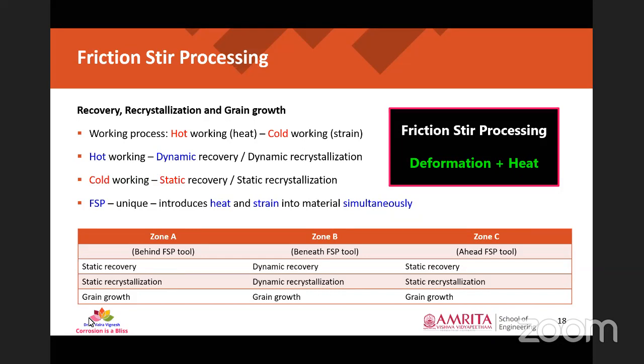Okay, so generally speaking, materials working processes could be classified as hot working and cold working processes. In hot working, the grain structure refinement will be through heat input, and in cold working, that will be through strain. In hot working, dynamic recovery and dynamic recrystallization take place, and in cold working, static recovery and static recrystallization take place. But FSP is unique. Why? Because we introduce heat and strain into the matrix simultaneously, so that dynamic and static recovery and recrystallization phenomena take place in the material simultaneously. Okay, and this is the greatest advantage of the FSP process.